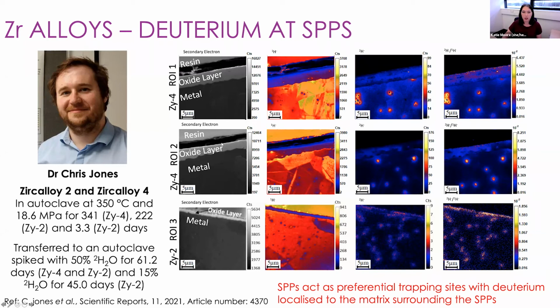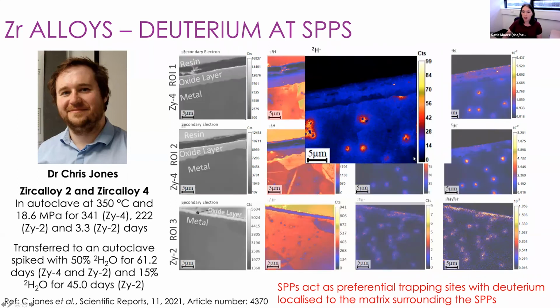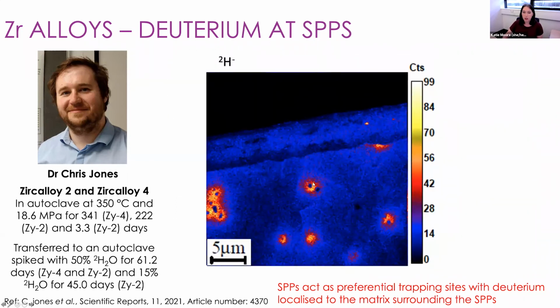So just like I showed you before, we have an oxide layer, looking at it in cross section, and the metal underneath. And it was very clear we could see all of these hotspots. If we have a closer look at one of these images, you can see there's a small hole in the middle of each one of them, just here. Now, these holes are actually the location of secondary phase particles in the zirconium, and we can very clearly see the deuterium localizing around them.